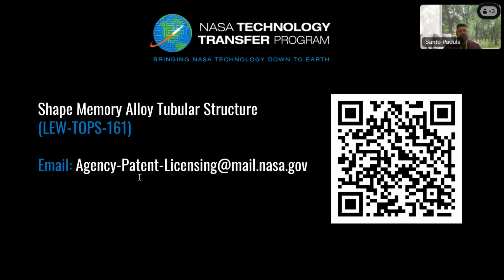We can do that effect currently with the alloys and processings that we have today in production. We can do it everywhere from about minus 130 or 150 C all the way up to close to about 400 C repeatably. I'm currently working on new classes of alloys that will let us extend that down to about 40 Kelvin, which is a little bit beyond minus 230 C. And again, we're working on other alloy systems that will let us go the other way to extend this capability all the way up to close to 800, 900 C, for the mechanically induced transformation. The thermally induced transformation is slightly different, and so the answer there is slightly different, but we're working on ranges of alloys that are going to allow us to go over pretty much anything you could think of.